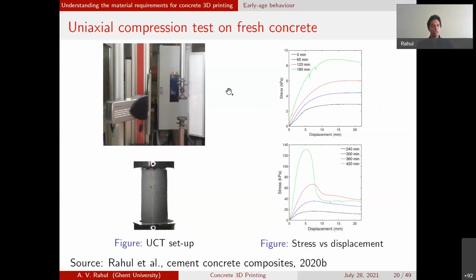So how can we do that? One of the ways is to do a uniaxial compression test on fresh concrete. This is illustrated here. In this setup, we have a cylindrical specimen which is immediately demolded. It is freshly cast and then immediately demolded. The cylinder can retain its shape because the 3D printable concrete is stiff, unlike conventional concrete. Then it's placed in a video extensometer system like this, and both longitudinal as well as lateral displacement are characterized using the video extensometer system. Here, I should point out that the lateral displacement characterization is required because, unlike hardened concrete, a lot of lateral deformation occurs in the material.